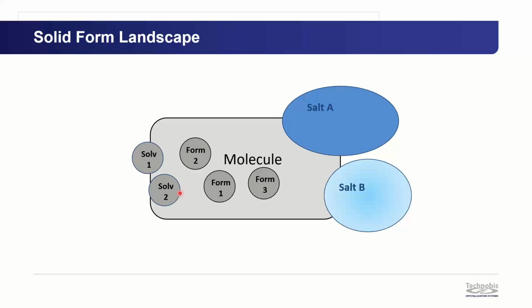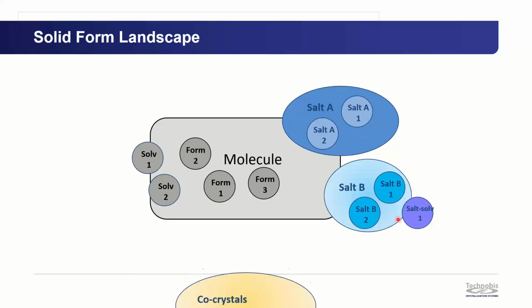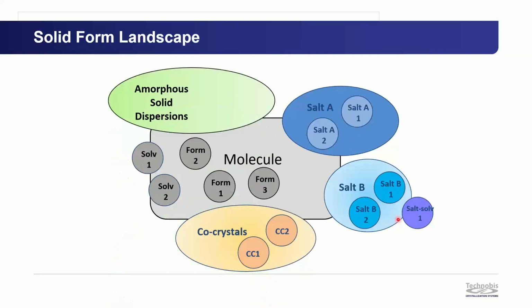However, it's sometimes considered, and wrongly, that by forming a salt or a co-crystal, you actually reduce the chances of polymorphism. And this isn't the case. You'll tend to find that if you're getting polymorphs of the main molecule, you're also likely to get polymorphs of the salts. I mean, in some cases, salt solvates or co-crystals and co-crystal solvates being formed.